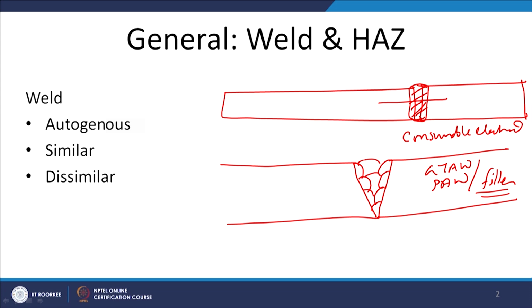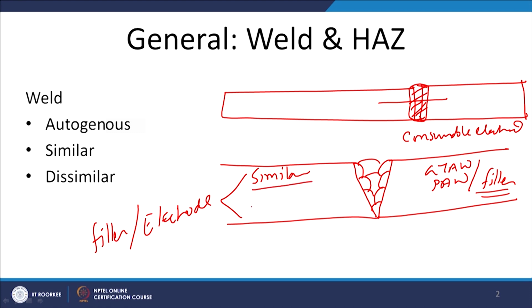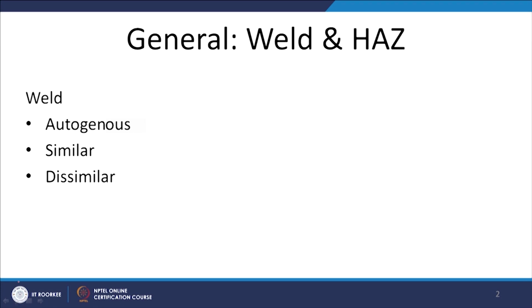So, this filler or the consumable electrode can be of two types. The filler or the electrode composition can be almost similar to that of the base metal, or it can be completely different than the base metal. So, in most of the cases when there are no major metallurgical issues and weldability issues related with the base metal, then mostly the matching filler or the electrode metal is used. But if you want to address some specific technological aspects related with the poor weldability of the base metal, then we choose the dissimilar or completely different filler metal or the electrode.